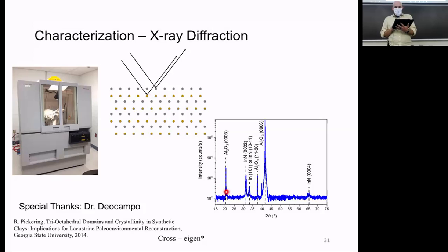So you can see these peaks here. This one corresponds to sapphire, which is the substrate that we grew on. And these ones here correspond to indium, or in this case, indium or indium nitride. And that's kind of the fun thing about science. Some people say that this peak in this pattern corresponds to indium, and some people said it corresponds to indium nitride. And who's right? It's a good question.